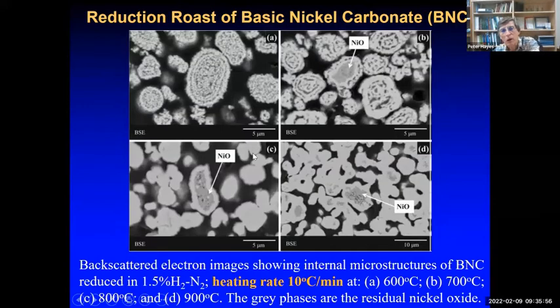Okay, let's take a real case of reduction of nickel oxide and look at what happened in a situation not where we have isothermal tests, but where we have an increasing temperature. So starting off with a basic nickel carbonate, as we go up in temperature, that decomposes into nickel oxide in these very fine granules here. This basic nickel carbonate is formed from a hydrometallurgical process, and when we heat them up, these granules change to nickel oxide. Now you can see at low temperature, we've got this very fine porous nickel layer, and you can see some of the traces of the onion rings, if you like, which reflect the decomposition and the precipitation of the basic nickel carbonate.